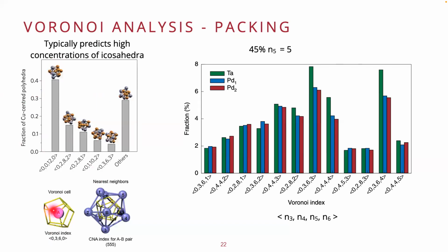where you have these 13 atoms that all have 5-fold symmetry clusters. But what we see in our experimental data is that's not the case, right? We know that 45% of our short range ordering has 5-fold symmetry. They're just not aggregated into these perfect icosahedrons.